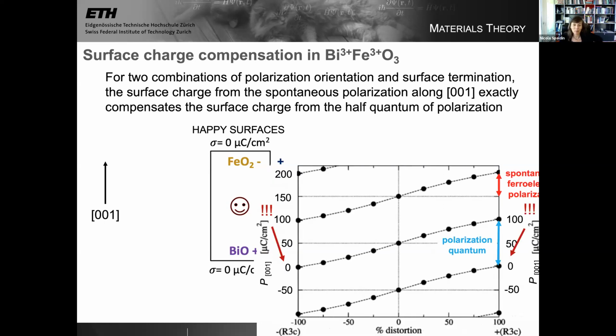We should have realized this in prehistory when we first made this calculation, and I pointed this out to you earlier, that the total polarization, of course, normally when one calculates the polarization of a ferroelectric, one's only interested in the spontaneous ferroelectric polarization. And this was indeed what we were interested in at the time. But the total polarization can actually be zero, because in this calculation one has, of course, all the ions there. So the system knows about the internal charged layers. And bismuth ferrite in its bulk ferroelectric state can have a total polarization. One of the allowed values is actually zero. And this manifests in these happy surfaces.